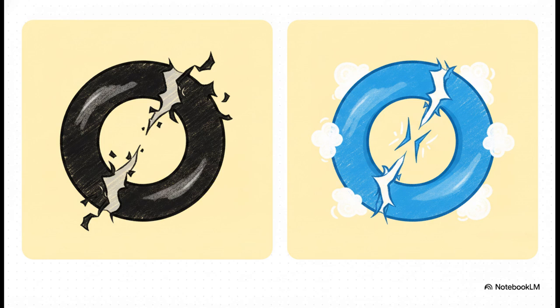If you scratch a PVD coating, the color is gone for good. The raw metal is exposed, and the coating might even start peeling back from the edges of the scratch. But if you scratch an anodized piece, you're really just removing that local oxide layer. And here's the brilliant part. Because it's titanium, that protective oxide layer naturally reforms itself just by touching the air at room temperature. The scratch won't spread, and the finish won't peel because there literally is no separate layer to peel in the first place.